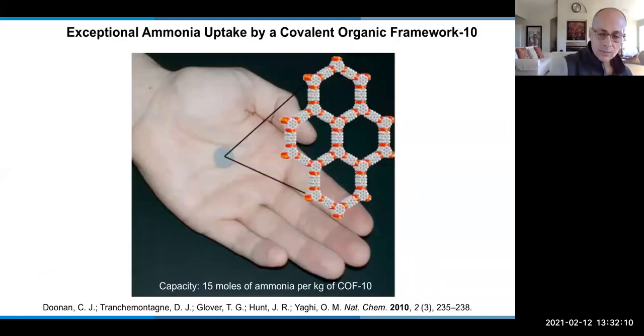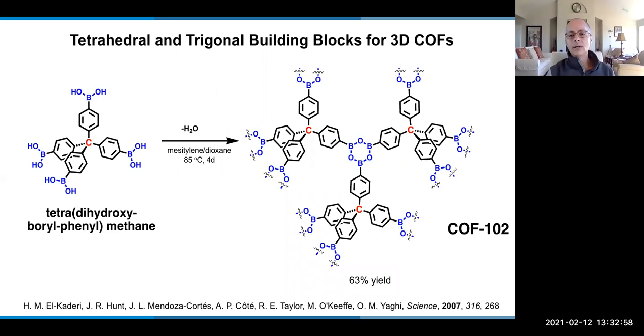One of them, the COF-10, the last one I showed you there, we tested and examined its chemistry with ammonia, and it turns out it takes up tons of ammonia. So 15 moles of ammonia for each kilo of COF-10. We reported this back in 2010. And here a student is holding a pellet of COF-10 that is filled with ammonia. And many people who work with ammonia know that ammonia is a corrosive liquid as used in the laboratory. And here we're holding it at room temperature and under ambient conditions, very nicely contained within the solid. So those were 2D COFs.